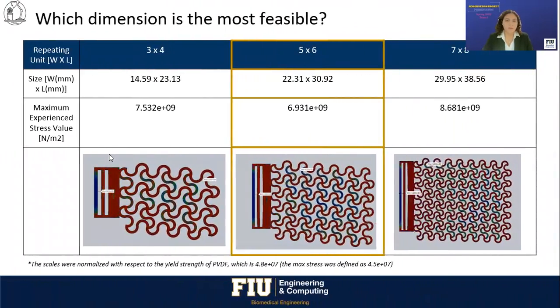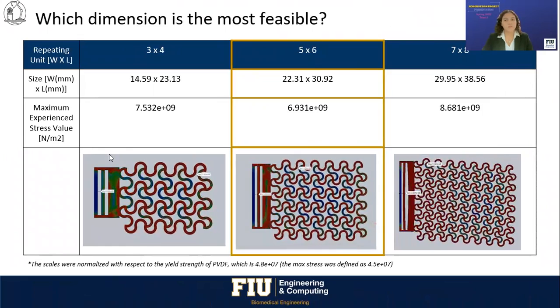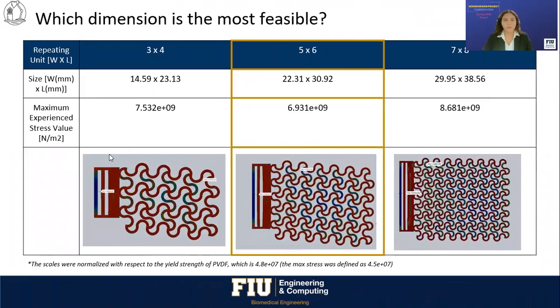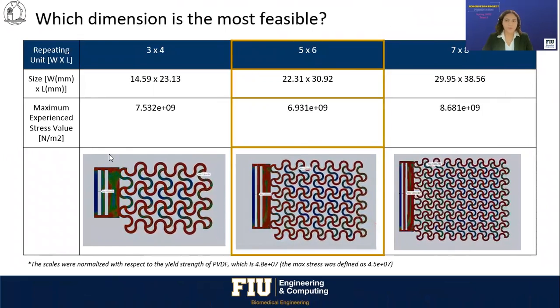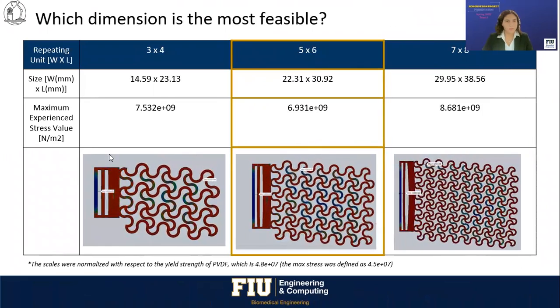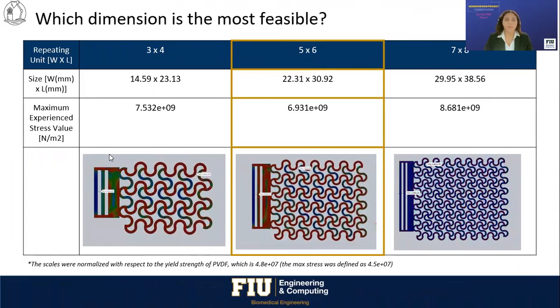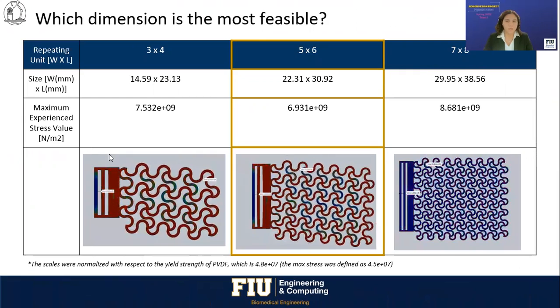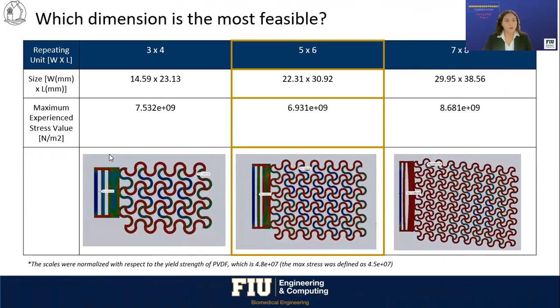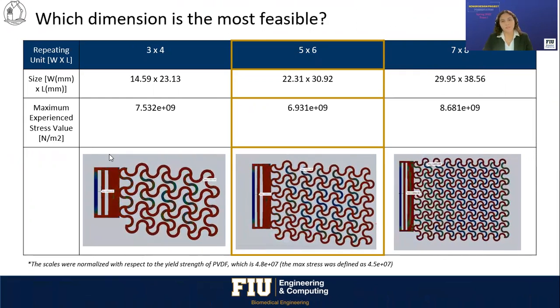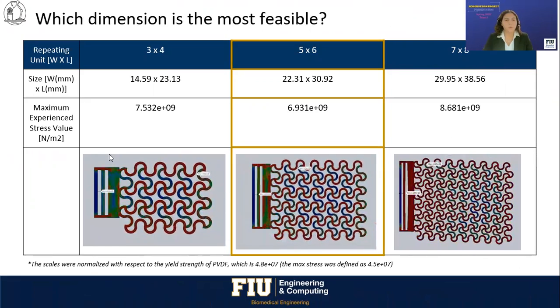We then looked into the dimensions of the sensor. The analysis used the same setting as the previous one, but compared 3 different sizes. As shown, a size of roughly 22 millimeters by 31 millimeters was within the width limitations and had the lowest maximum experienced stress value. Our next analysis looked into the varying dimensions with respect to the output voltage, which I will pass on to Hania.